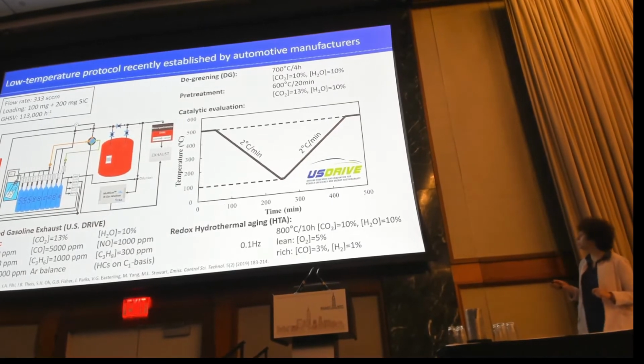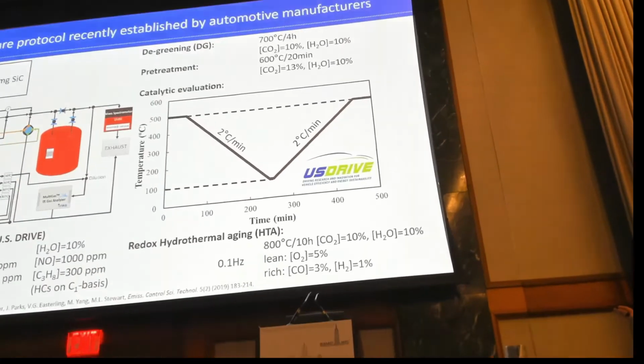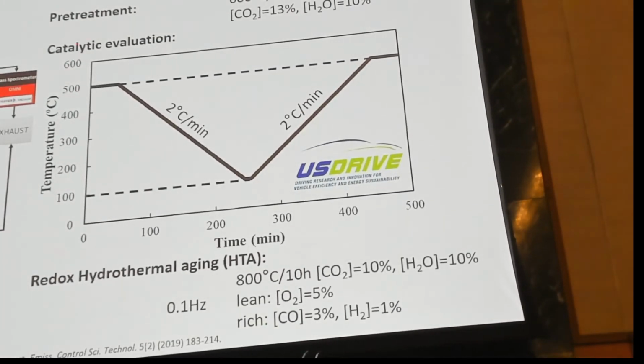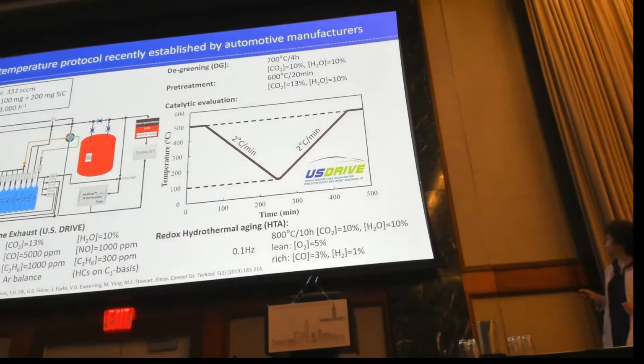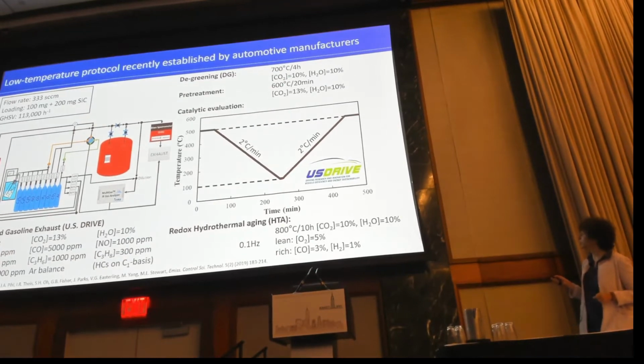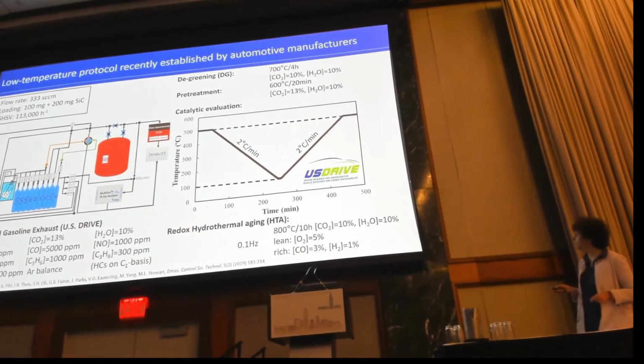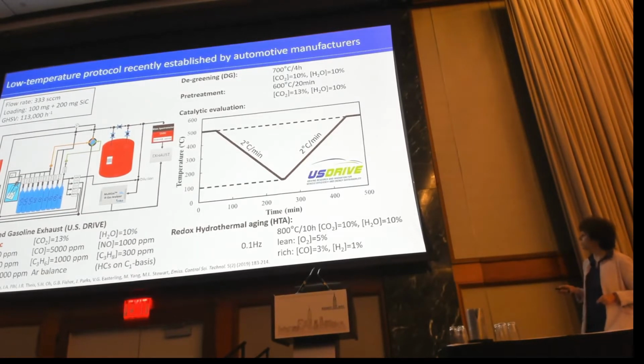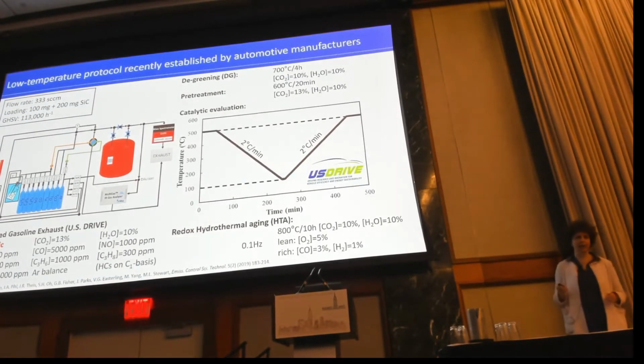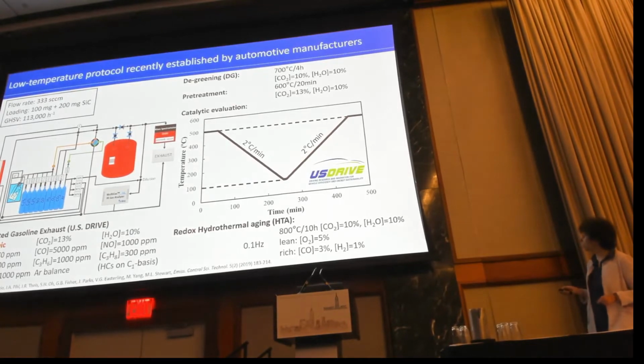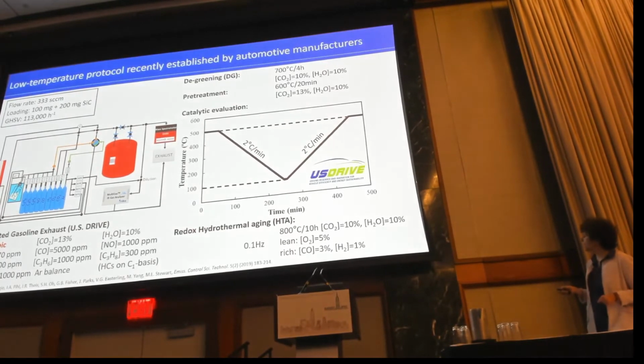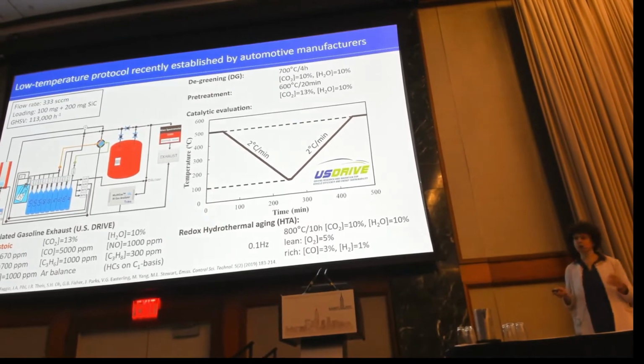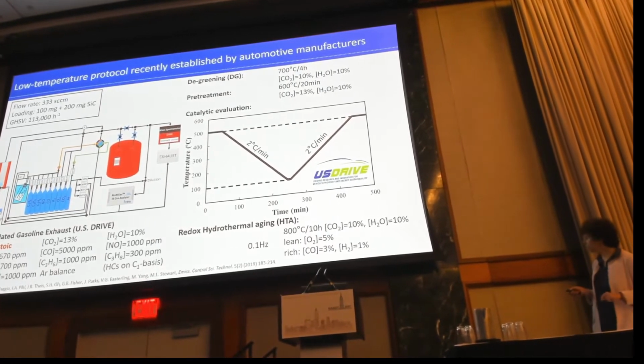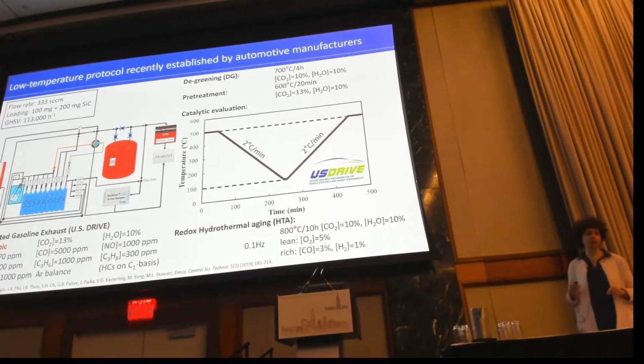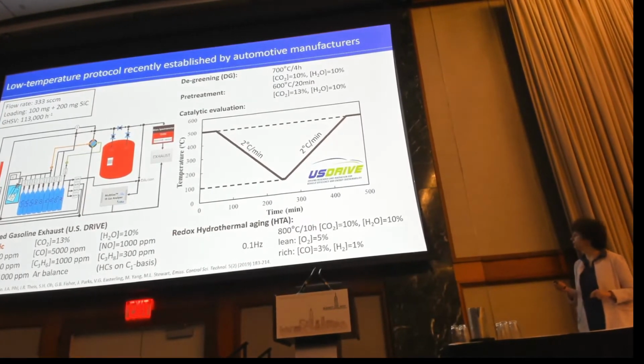Okay, so here's our protocol. We're doing degreening at 700 degrees C for 4 hours. The conditions are here. Pre-treatment is 600 degrees C for 20 minutes. Then you're cooling down to 100 degrees C, heating up to 500 degrees C. The ramp rate is 2 degrees C per minute. Now, in this case, for the three-way catalyst, we're doing a redox hydrothermal aging, which is a severe hydrothermal aging. We expose the catalyst to 800 degrees C for 10 hours, and we are doing a lean-rich switch every 10 seconds. Okay? So it's a severe hydrothermal aging that the catalyst tends to be activated under usually under these conditions.